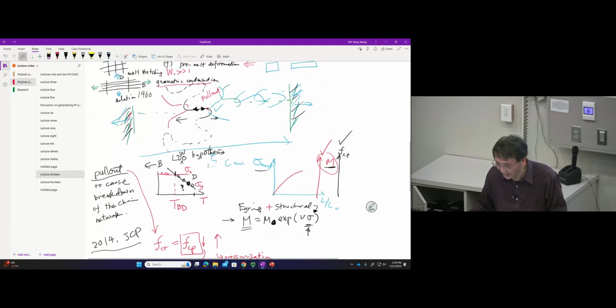I tried my best to say that ductility is about having a network that delivers the stress that can mobilize it. If the temperature is too cold, the job cannot be completed by the network, because the network will see itself building too much tension and they fall apart through chain pull-out. That's it. And that's why you have this side brittle, this side ductile.